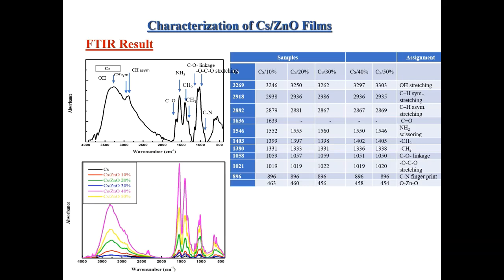For chitosan zinc oxide sample characterization, according to the FTIR spectra, the main features of the molecular structure of pure chitosan are shown in the figure, and the main characteristic bands of chitosan are listed in the table. The presence of zinc oxide affects the chitosan spectrum by shifting bands to higher wave number, besides the disappearing of the C=O band, with the appearance of a zinc oxide band around 450 cm-1, which confirmed the interaction between zinc oxide and chitosan through the NH2 group, which makes a change in molecular structure from acetyl to diacetyl chitosan.